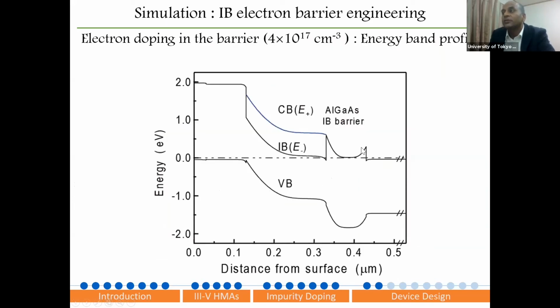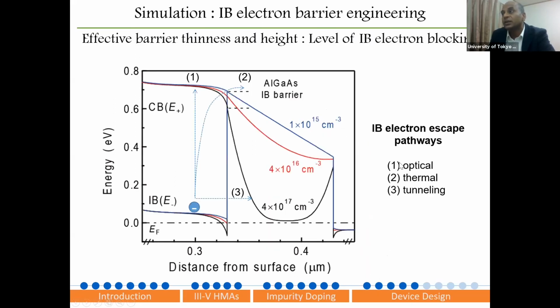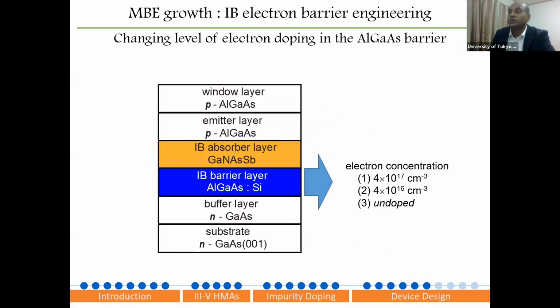Let's say here is a barrier layer, and this is my dilute nitride material, and this is my contact layer, backside and front side. The electron coming here should not pass through, but if I have a very thin barrier here, my electron will tunnel through. But if you play with the carrier concentration in your barrier, the barrier becomes very thick and the electron cannot pass through. If the carrier concentration in the barrier is very, very high, then you can stop the tunneling. By changing the carrier concentration in your barrier layer, you can play with barrier engineering, and you can confirm whether your material is really an intermediate band material or not. And this is the idea.